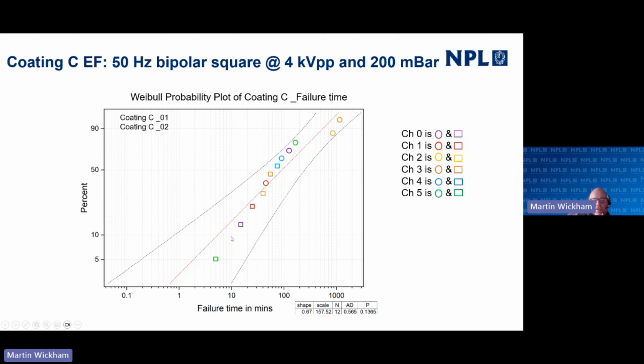This shows the Weibull plot. In this case, for the first set of samples, we're seeing the voltage tends to be lower than the second set. Potentially there's a set of data here that all occur on a straight line, and then there's two outliers here, but they all fall within the 95 percentile line. So we've just shown them as a single line here, but if you're going into this in a bit more depth, you might break these into two populations. You can see here that generally speaking, they do overlap, but mostly the second sample doesn't behave as well as the first sample does.